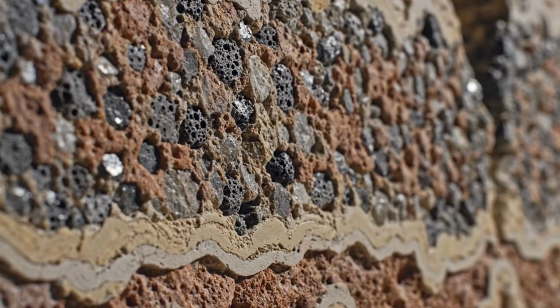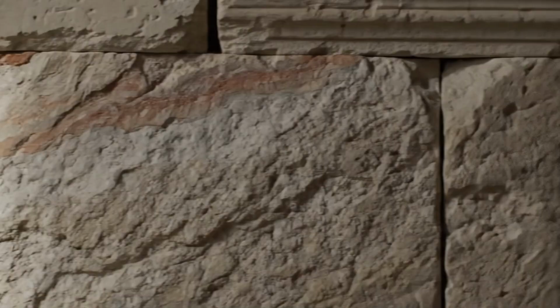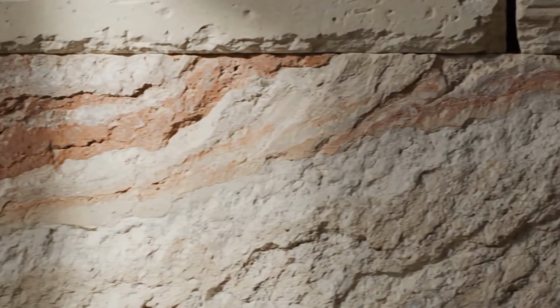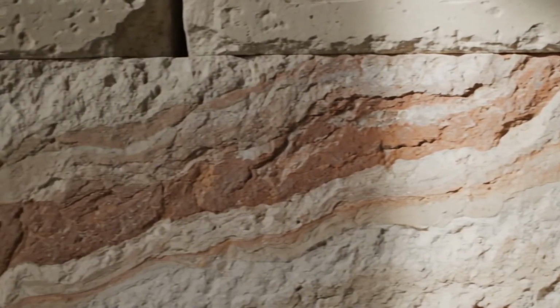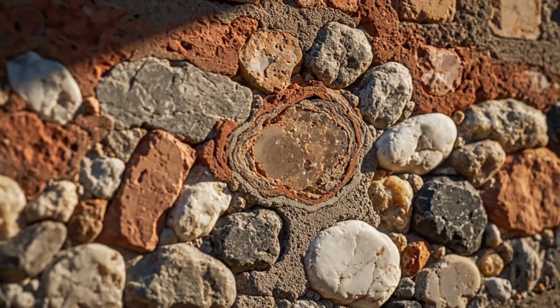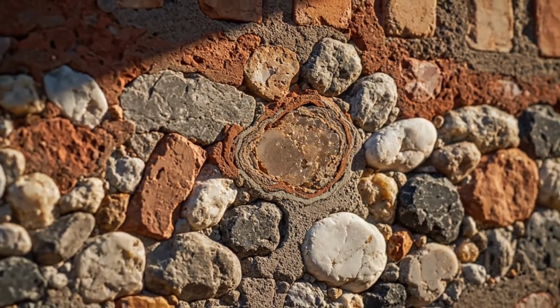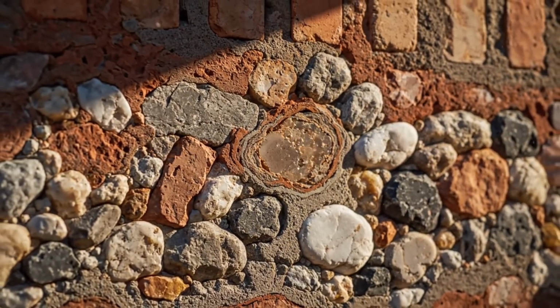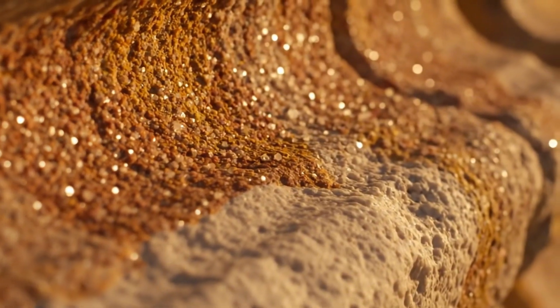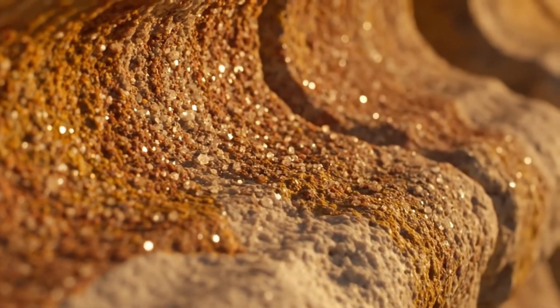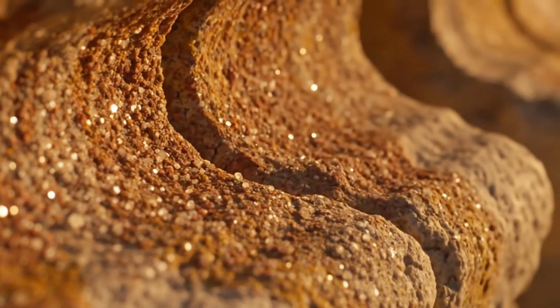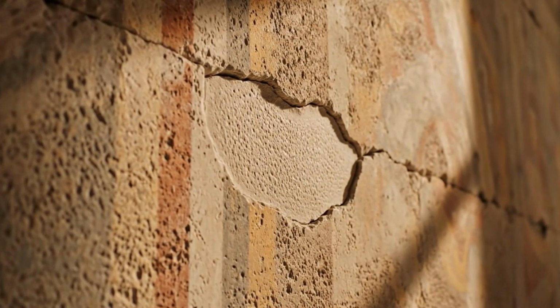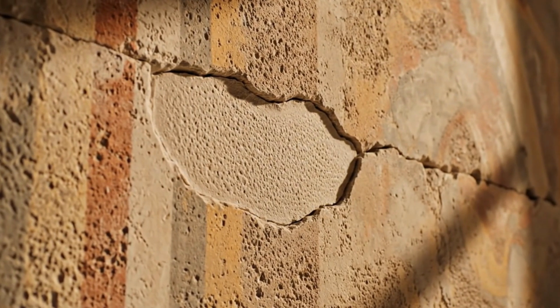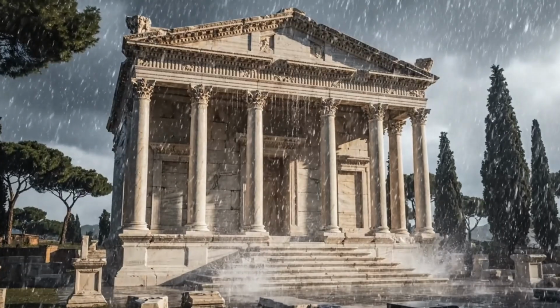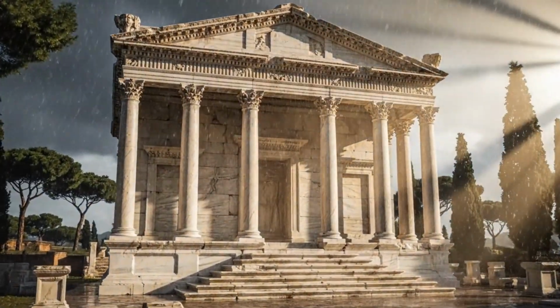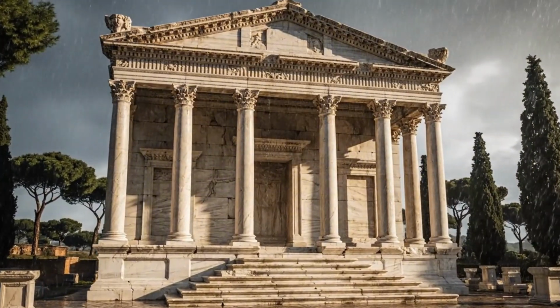The evidence emerging from the studies of Roman concrete presents a different pattern. In the Tomb of Caecilia Metella, researchers observed that the interfaces between volcanic aggregates and the surrounding mortar did not simply remain intact by chance. Instead, they appear to have undergone a slow and continuous remodeling. As potassium released from dissolving leucite interacted with the calcium-aluminum silicate hydrate binding phase, the microstructure of the mortar evolved. Nanocrystalline domains formed, and the bonding regions between aggregate and matrix were reorganized. Rather than swelling and separating, these zones seem to have become more cohesive over time.